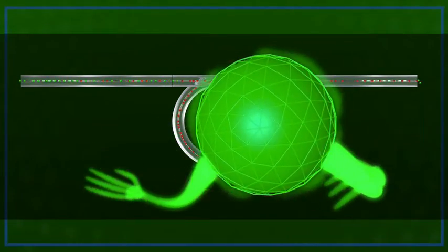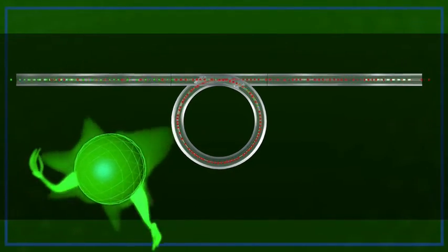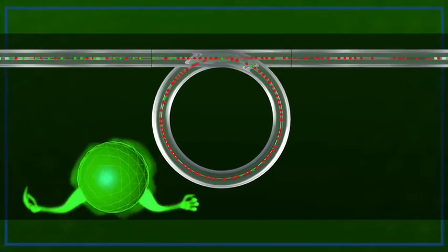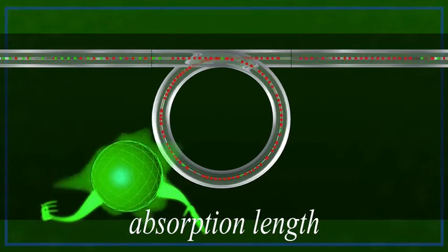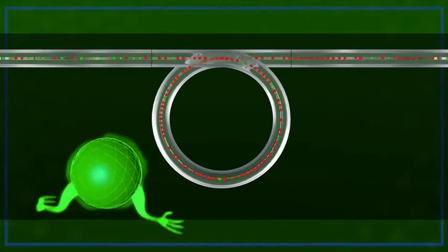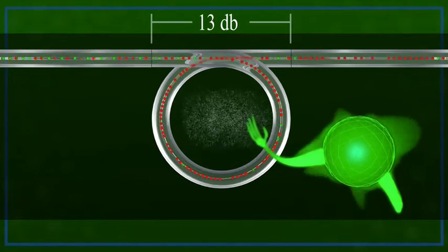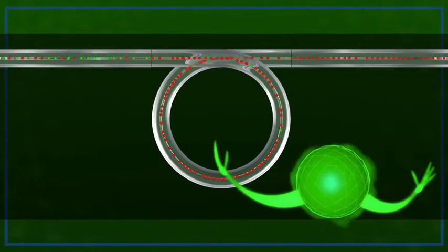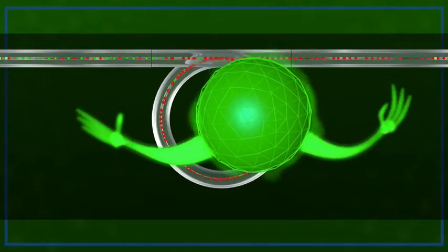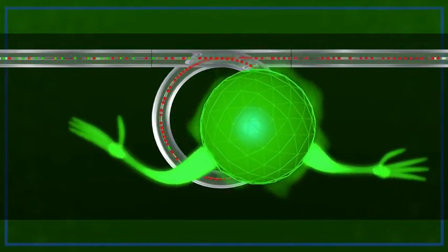Monolithic in fiber terminology means that once the light is in the fiber, it stays in the fiber, end to end. However, the length of the doped fiber is important as it determines how much of the pump light is absorbed. We use the term absorption length for the combination of length with the amount of doping. Typically, a fiber laser has an absorption length of about 95% of the pump energy. This is to avoid having a section of unpumped fiber in the laser cavity. An unpumped section inevitably charges itself and self-lases, resulting in a failed fiber.